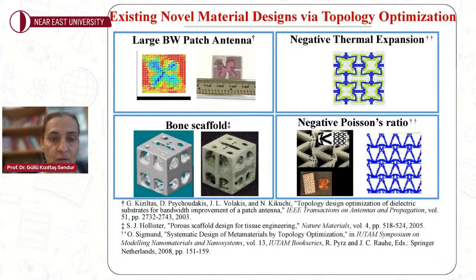In parallel to this observation, our early efforts showed that novel material designs through topology optimization are actually able to deliver novel response that you could not achieve using ad hoc trial and error with only the usage of available material in a homogeneous fashion. You see here examples of our earlier design schemes that were able to distribute the material. Each color code is a different material that we were able to fabricate using certain die-cast type of polymer and the ceramic, and deliver the novel response that a homogeneous substrate could not do.